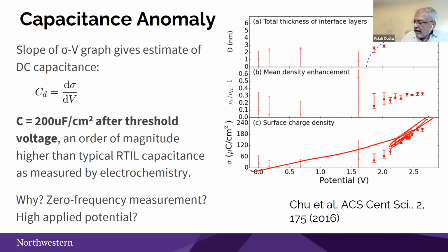Here's what's interesting. If you look at this slope, it's about an order of magnitude higher than the AC capacitances, okay? You remember my showing you the double humped pictures, and of course those numbers vary with the particular liquid used, they vary with the voltage, but ballpark they're 10, 20, 30 microfarads per centimeter squared. But if you look at this number, it's 10 times as much, okay?